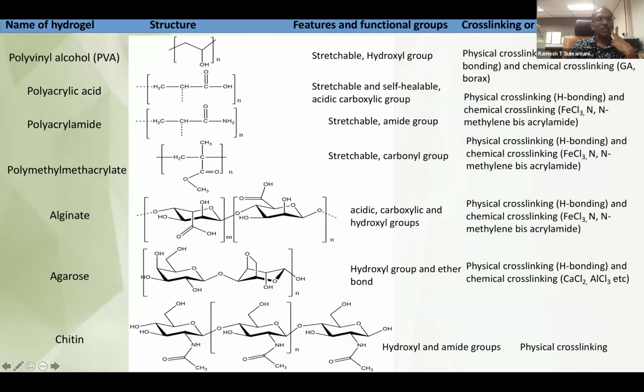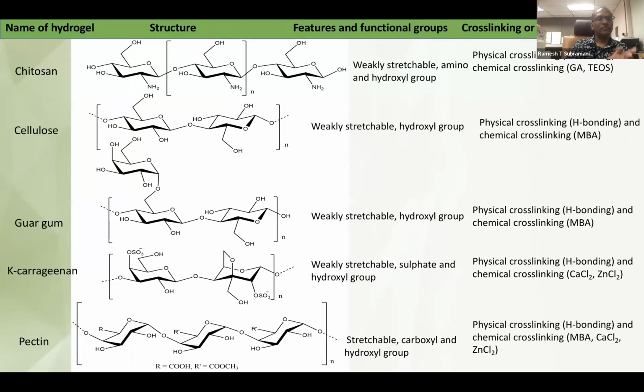Okay, here are some of the examples. For example, polyvinyl alcohol. We can purchase polyvinyl alcohol from the supplier itself. Or just say we want to make it as a hydrogel. If we follow the steps given here, by selecting the appropriate initiator and appropriate cross-linking agent, we can convert the polyvinyl alcohol to become a hydrogel polyvinyl alcohol. We can do this for many different types of polymers, natural or even synthetic polymers. Natural polymers like chitosan, cellulose, and guar gum can also be converted to become hydrogel polymer electrolytes.